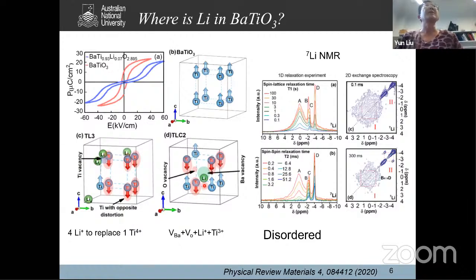Another possibility is the lithium will induce the titanium reduction from 4 plus to 3 plus, and also form a cluster with 1 oxygen vacancy, 1 barium vacancy. So that's correct. Because lithium is chemically unhappy in this barium titanate, locally they will change the chemical environment. As a result, unlike the pure barium titanate, where all titanium moves in one direction to give you a ferroelectric property, you have opposite titanium ion displacement. So that gives you an anti-ferroelectric type physical property.